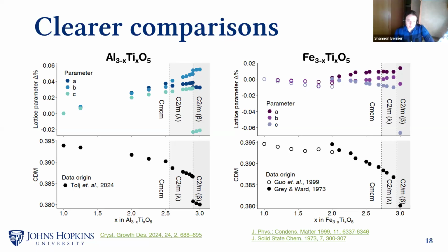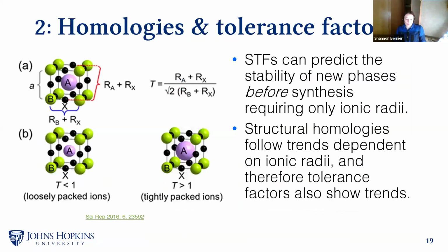All right, well, if there are no more questions on this case study, I'll speak about the other ones. I mentioned earlier that we wanted to set up our cubic deviation metric in contrast to what's called a tolerance factor. Structural tolerance factors are used, and I would argue abused, a lot in our field. They're basically empirical metrics that are designed to predict whether a combination of atoms will crystallize in a particular space group before you have made them. And as such, they take as inputs only the atomic radii of the components of that structure and their proposed packing arrangement. The most famous one is the Goldschmidt tolerance factor, which was made in 1926, and that's this guy right here.